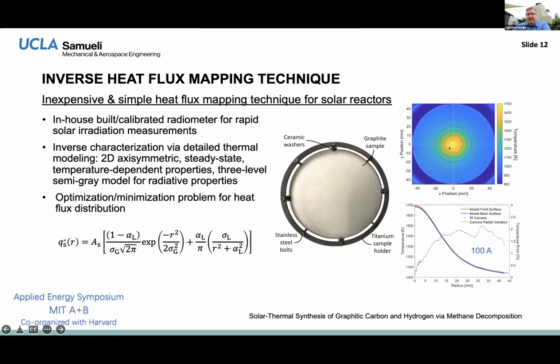We have a very, very large temperature gradient across our thin absorber. In this case, the absorber is graphite. Later on, it'll be our porous material. But when I first saw that, I thought, oh, that's not very good. Usually in a reactor, you want to have a relatively uniform temperature. But then as we developed results, we found that it was actually a blessing in disguise, because we have basically